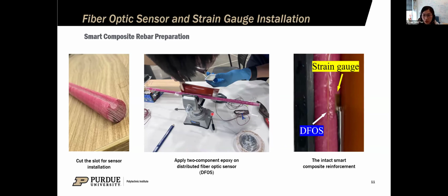So we have 2 ways here. The first one is we create a groove on the composite rebar, and we insert the silica tube in the groove and put the fiber optic sensor in the tube. And the second way is we use a thick layer of epoxy coating and attach the fiber optic sensor cable on the rebar using the epoxy coating to protect the fiber optic sensors.